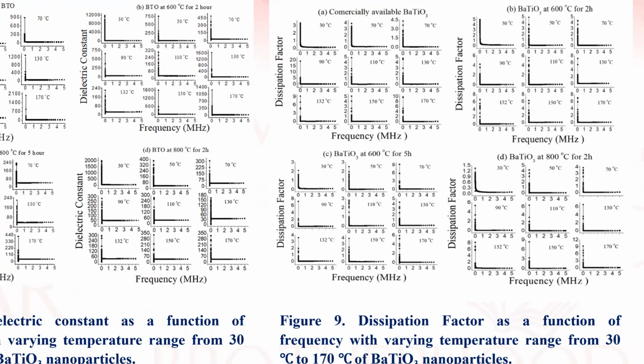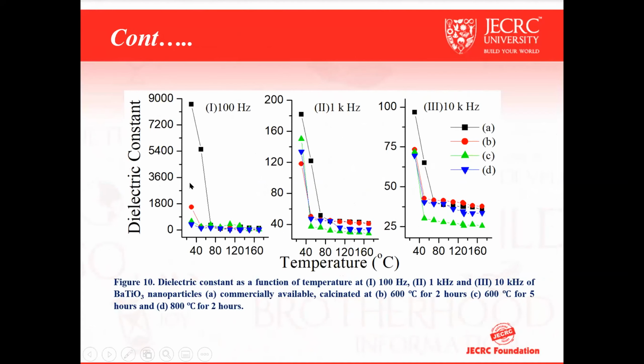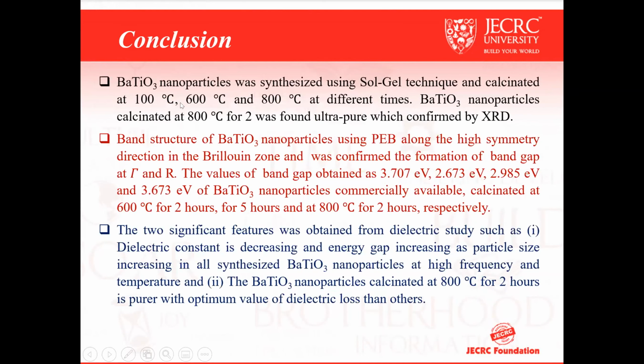If we compare the dielectric study at specific frequencies, we have taken three: 100 hertz, 1 kilohertz, and 10 kilohertz. What we observe here is that the dielectric constant decreases with increasing frequency initially, and then becomes almost constant. This is maybe due to the calcination effect on the barium titanate, and the finding is that 800 degrees centigrade for 2 hours gives an optimum value of dielectric constant.